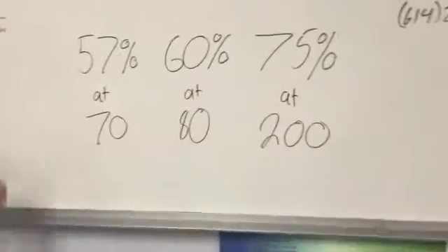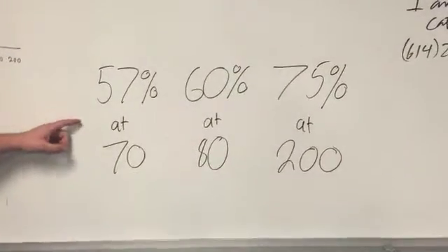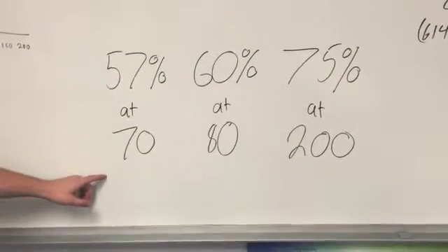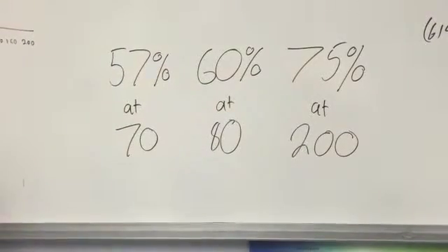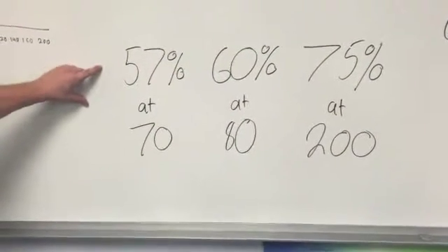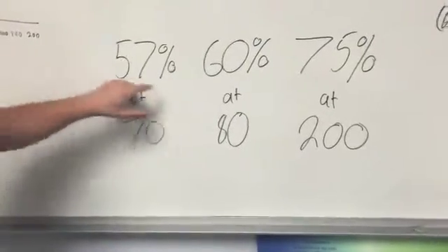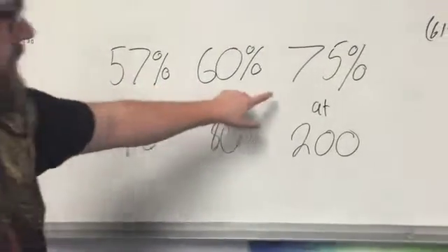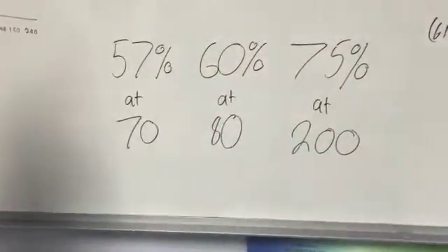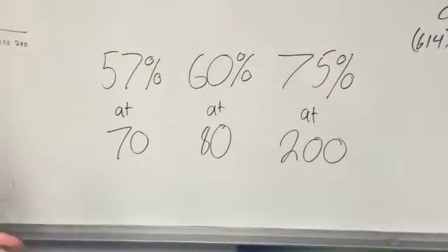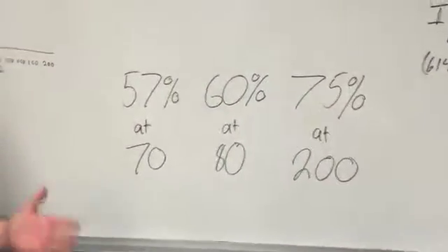Over here, we broke down the actual percent errors and what they're actually supposed to be. So our percent error for aluminum is 57%. As we go higher in what the Young's modulus is supposed to be, the percent difference actually increases. This leads us to believe that there is a type of exponential error happening with the calibration of the machine.